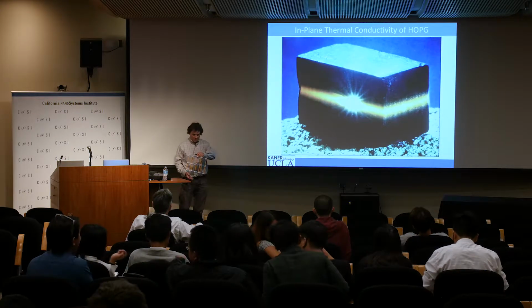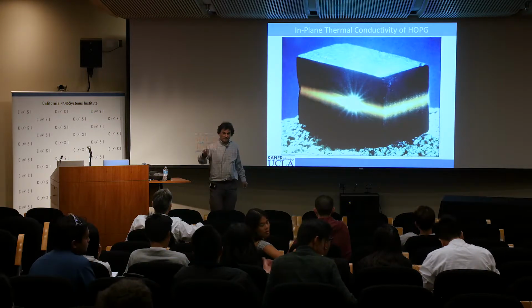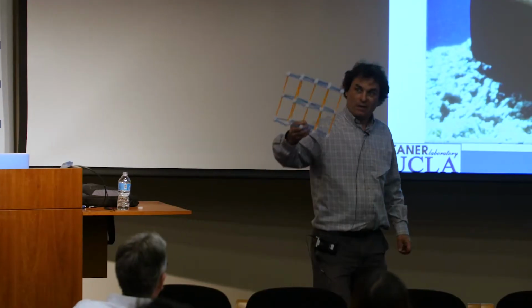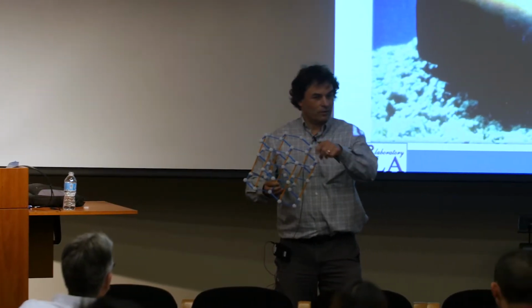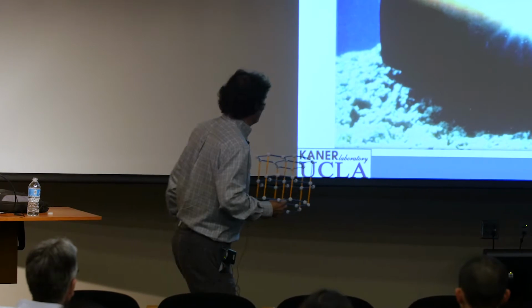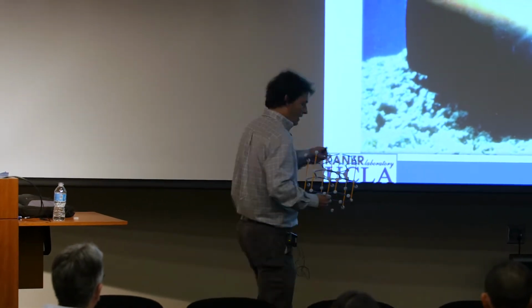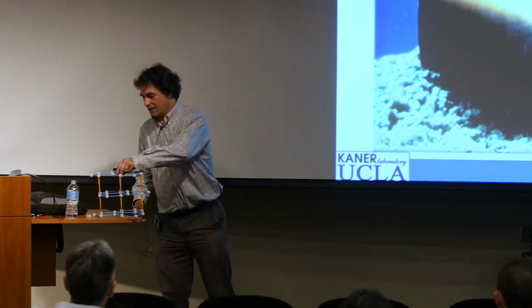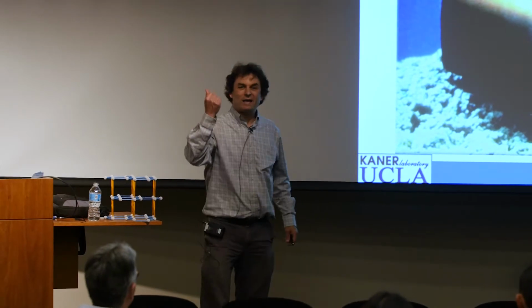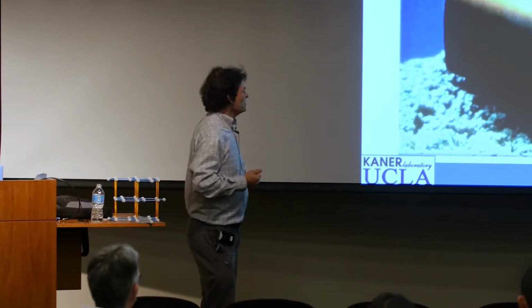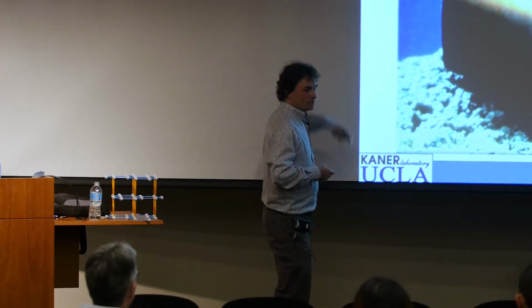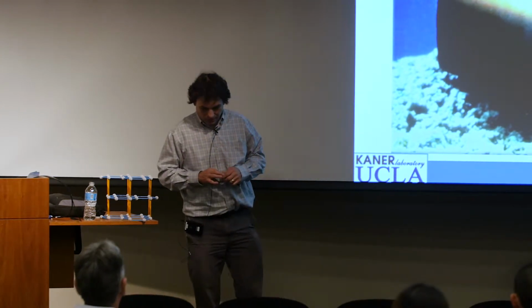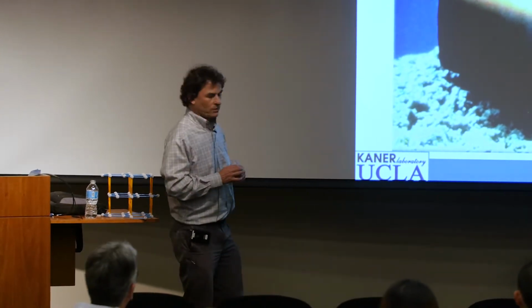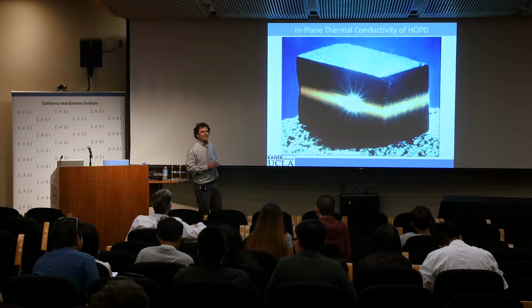So here's my favorite picture of graphite. In fact, here's the structure of graphite. And of course, graphene's just this top layer, which you'd peel off. But this is a block of pyrolytic graphite. This is what Novoselov and Geim used with Scotch tape. And this is about the size of your thumb. And what we're doing here is hitting it with a laser. This is from Neil Bartlett's lab where I worked about 30 years ago as a postdoctoral fellow. And this is being hit with a laser.